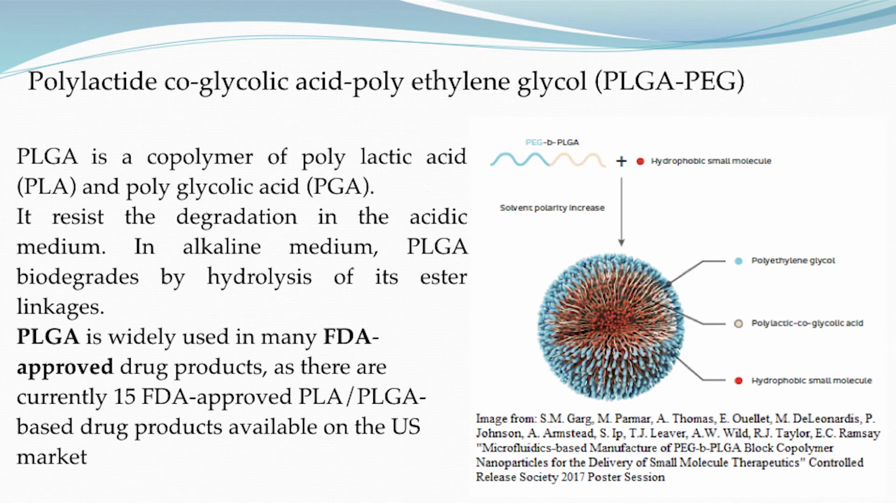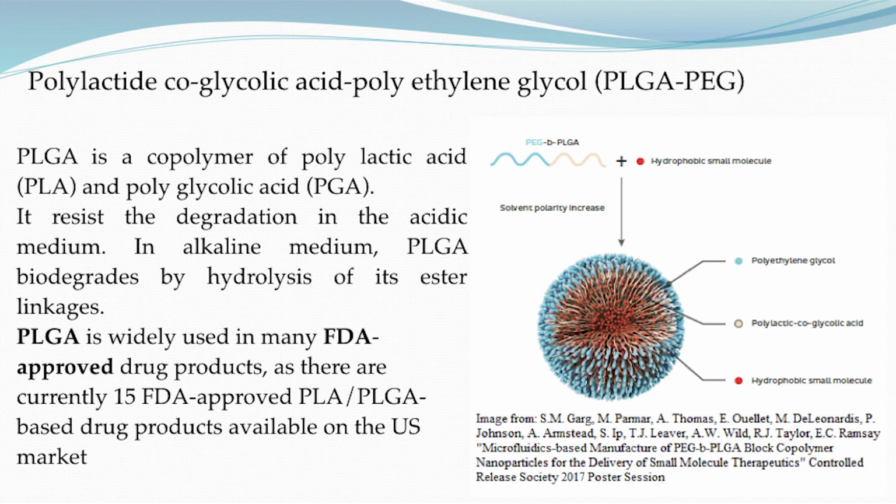The nanoparticles which successfully managed to penetrate the Candida biofilm were formed from a polymer called PLGA-PEG, which is the abbreviation for polylactic-co-glycolic acid linked with polyethylene glycol. PLGA is one of the polymers supplied by different companies, especially Sigma, and it is approved by the FDA to be used in food and in drugs. But when we fabricated the nanoparticles only from PLGA, the nanoparticles failed to penetrate the Candida biofilm. But after we added the polyethylene glycol, the particles managed to penetrate the Candida biofilm.